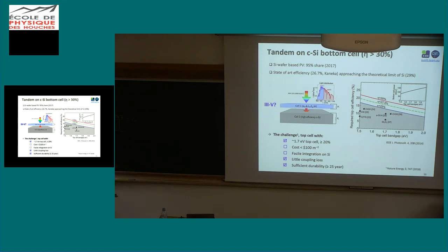And the question is, what would be the ideal top cell that we can stick on top of a silicon cell to make a tandem, so a multi-junction with 2 junctions, to have more than 30% efficiency, with relatively low cost, facile integration with silicon, little optical coupling losses between this cell and the silicon cell, and of course sufficient durability. So here you have this graph, which represents the required top cell efficiency to put on top of silicon versus the band gap of this top cell.